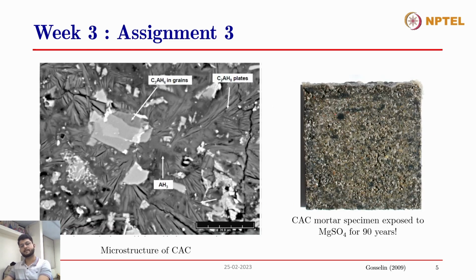And when you're using CAC or calcium aluminate cements, the hydration products that are formed in these cements are stable in the case of sulfates. When sulfate attack takes place inside the concrete, these hydrated phases are stable, and therefore there is no deterioration of concrete due to the sulfate attack. You can see this in this picture, taken from Gosselin et al., 2009. This is the microstructure of the CAC cement mortar specimen, which was exposed to MgSO4, magnesium sulfate, one of the harshest chemicals to cause sulfate attack in concrete, because it leads to brucite formation.